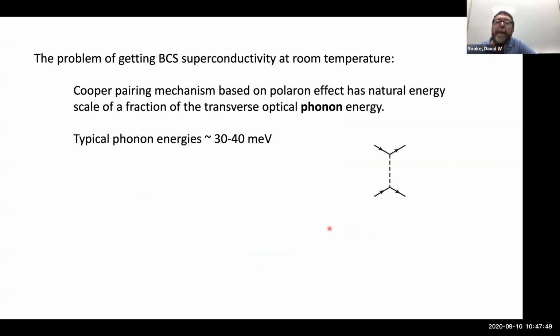And that's because the Cooper pairing mechanism uses a phonon as an effective boson to mediate the interaction. Typically, the strength of that interaction is going to be a fraction of the phonon energy. So if we have an optical phonon, typically in a solid, of 30 to 40 meV, this is going to give a TC of, say, 3 to 4 meV. And so it's going to be very hard to get high temperatures in BCS superconductors.